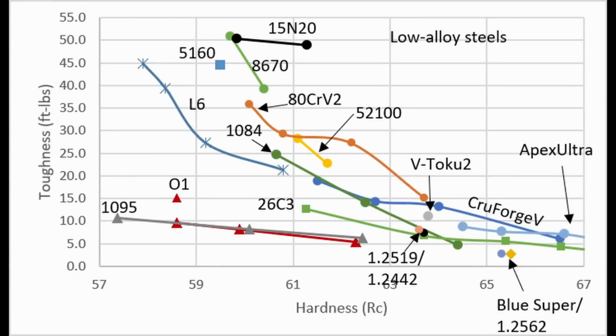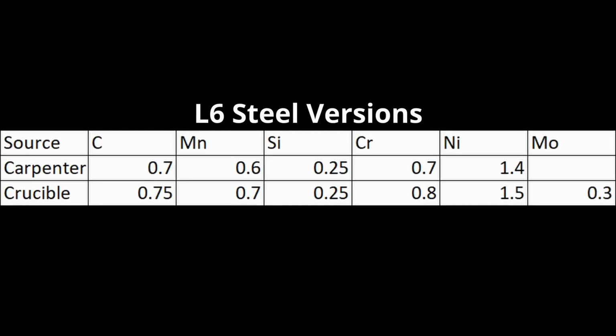Another steel we looked at was L6. Again, Warren, who has been a superstar with heat treating steel for these toughness tests, he looked at some L6 that he had gotten from New Jersey Steel Baron years ago. And we're not sure the ultimate source of this L6 either, though Warren did know that it was not the molybdenum version of L6. There's two major versions of L6. One comes from Carpenter and Latrobe without moly, and one comes from Crucible with moly. And this was the moly-free version.